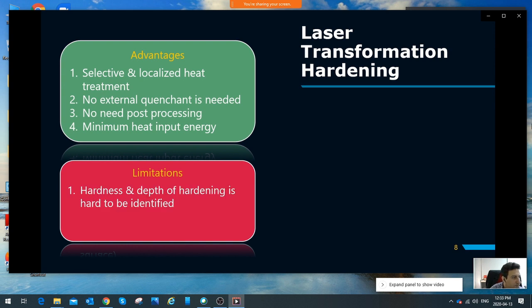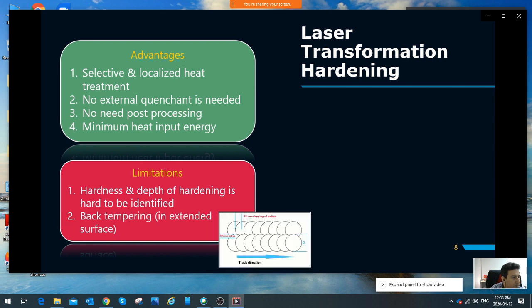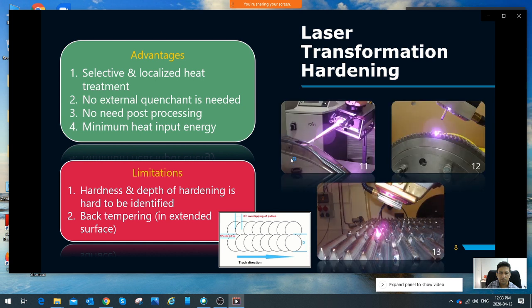However, there are some limitations. The first is that it is hard to identify the depth of the hardening, and the second one is back tempering. This refers to the hardness of the overlap part decreasing because of the overlapping laser track, as you can see in these pictures. And these pictures show the industry carrying out the laser transformation hardening process.